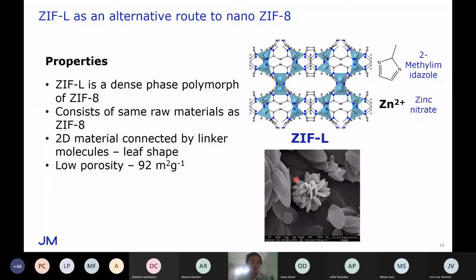We did find an alternative route, and that was using an intermediate material called ZIF-L. ZIF-L is a very similar material to nano-ZIF-8. It's this structure on the side here, and it's made from the same starting materials, 2-methylimidazole and zinc nitrate again. However, ZIF-L is a less stable material. It's actually constructed from 2-dimensional layers rather than 3-dimensional in ZIF-8. These 2-dimensional layers are held together through unreacted linker molecules. So we have unreacted 2-methylimidazole molecules between the layers of these materials, holding the layers together through hydrogen bonding.